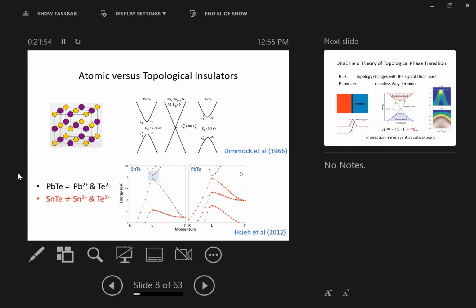Back then, it was conjectured that there is this gap closing and opening transition, but the consequence of this transition was not understood. It was also not understood which of the two, lead telluride or tin telluride, is an atomic insulator and which one is what we now call a topological insulator. This was sorted out about 10 years ago when we did the DFT calculations. And here I show you the band structure. As you can see, at low energy near the Fermi level, the bands have a linear-like dispersion, just like the cartoon schematics from almost half a century ago.